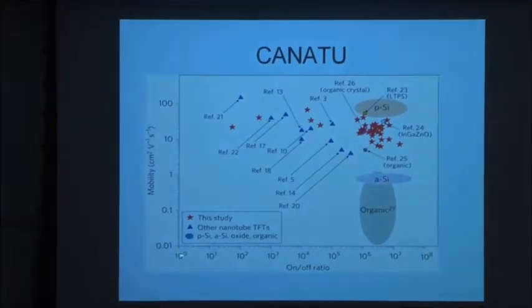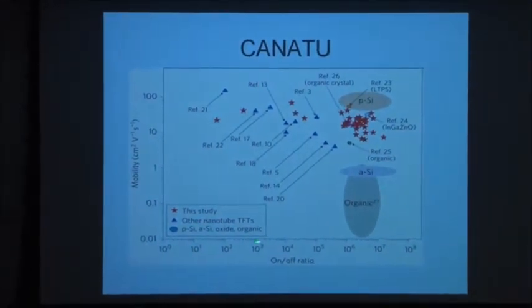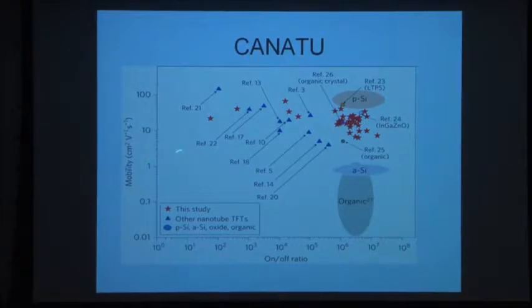And there's a company called Canatu in Finland who last year produced these results, which shows the on-off ratio for a bunch of transistors on plastic with their mobility. And this is a carbon nanotube. And you can see in this study, they've got mobilities of the order of 20, 30, 40 for carbon nanotubes on plastic. Now, there's not many other things when you put them in plastic that will give you mobility as high as that. So there's a big effort just now in trying to get plastic electronics to work.